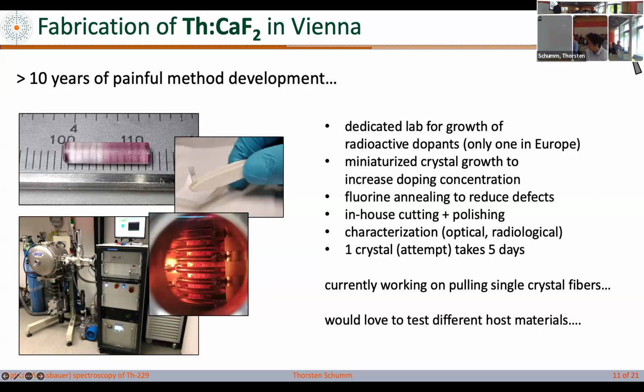So anyway, we drill this little hole, then we fill thorium fluoride into this little pot that has been prepared in our radiochemistry labs, which we can do because we have a nuclear reactor. Then we melt this to 1,640 degrees centigrade, but we only melt the top half. So this part becomes liquid, the bottom half doesn't. And then we have a phase interface, an interface between a liquid and a solid, because we have a half molten, half not molten crystal.